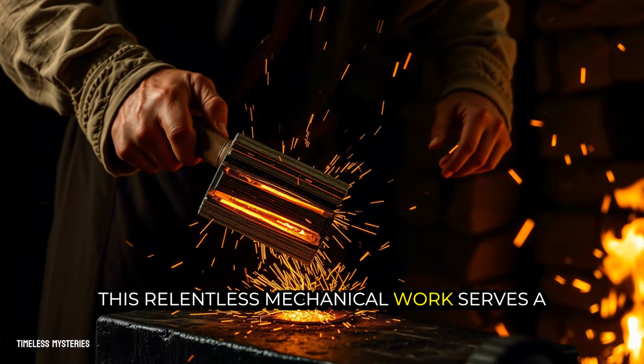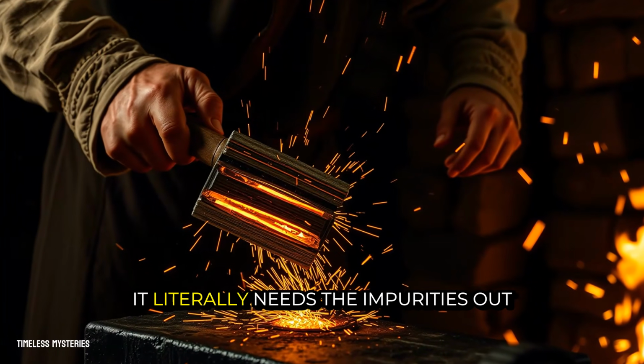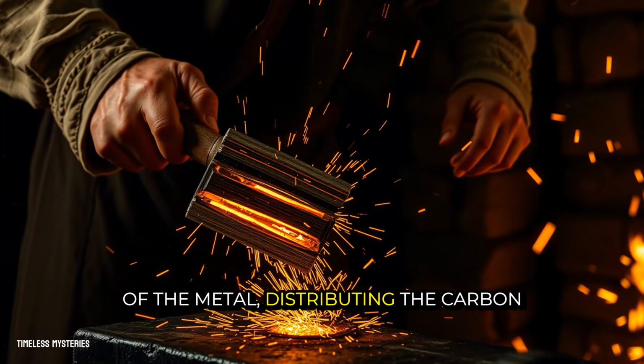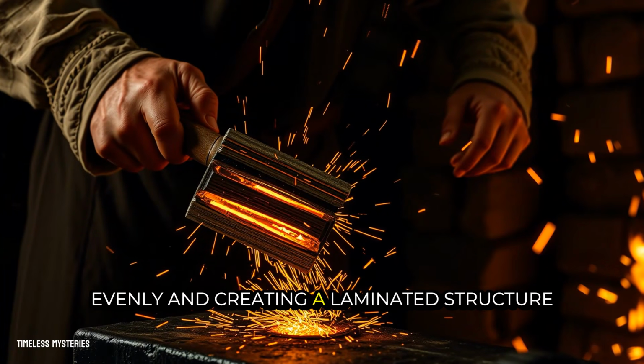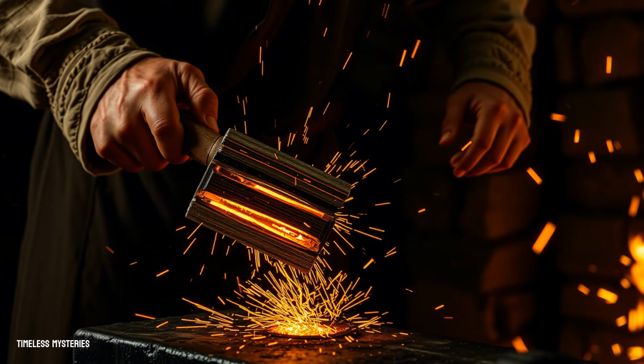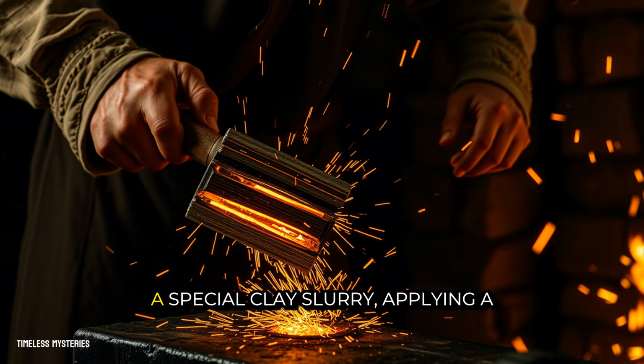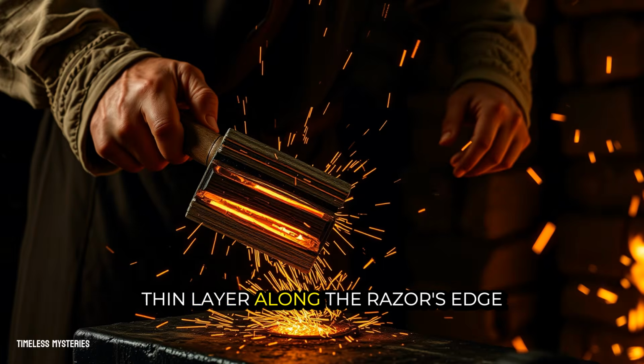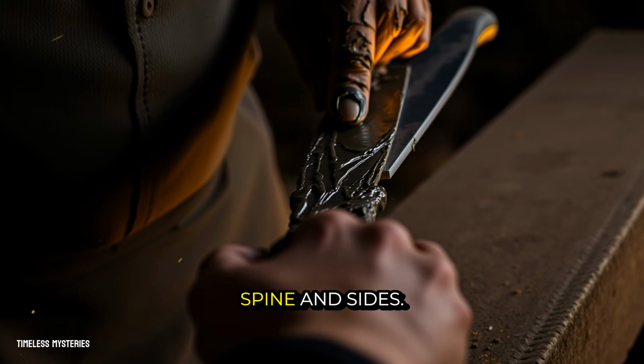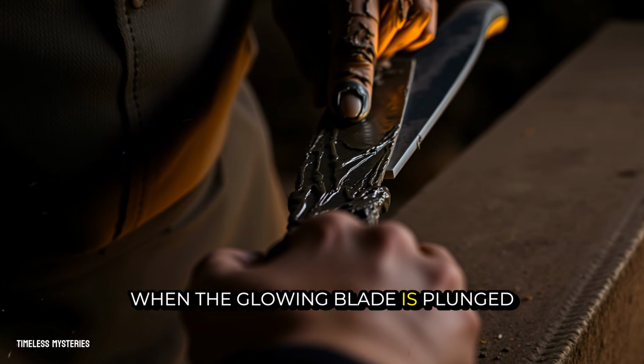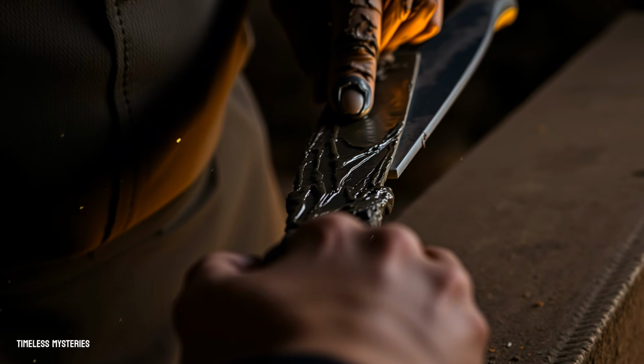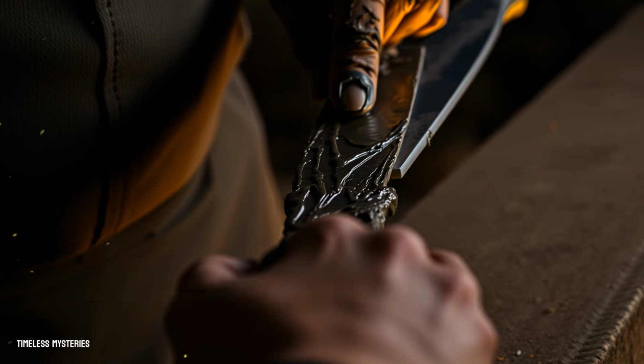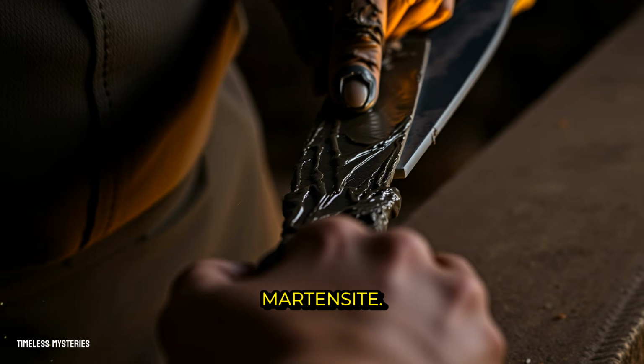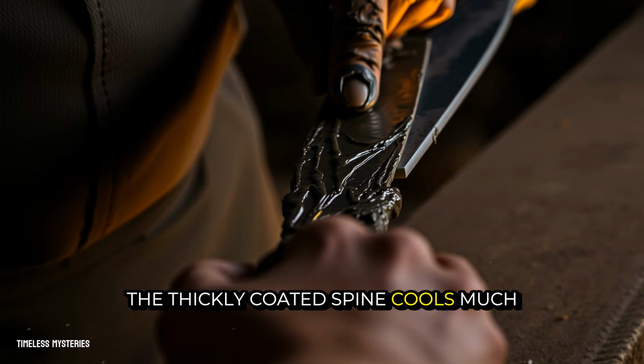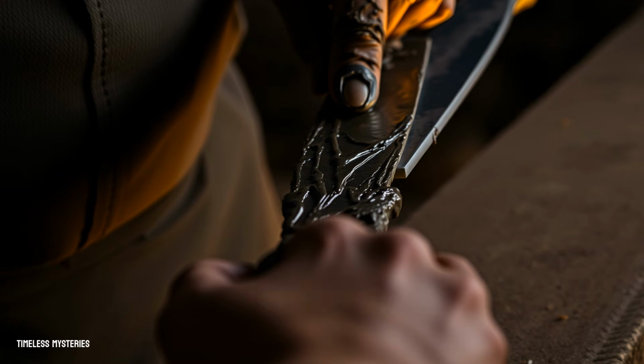This relentless mechanical work serves a clear purpose. It literally kneads the impurities out of the metal, distributing the carbon evenly and creating a laminated structure of astonishing uniformity. The true magic, however, happens in the quenching. The smith paints the blade with a special clay slurry, applying a thin layer along the razor's edge and a thick layer along the spine and sides. When the glowing blade is plunged into water, the thinly coated edge cools with shocking speed, transforming into an incredibly hard, crystalline form called martensite. The thickly coated spine cools much more slowly, remaining a softer, more flexible steel.